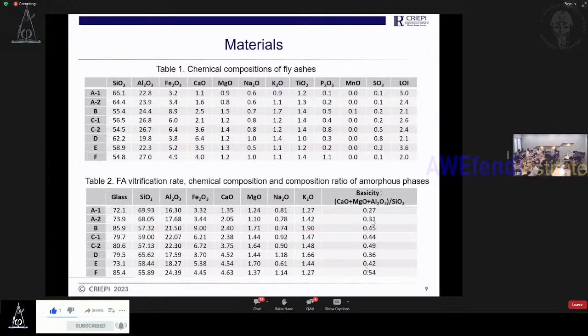The amount of glass is from 72 to 85%. I also show you the basicity, which is the ratio of the amount of calcium, magnesium, and aluminum to silica. The basicity is from 0.27 to about 0.5. There's much difference in the amounts among these samples.